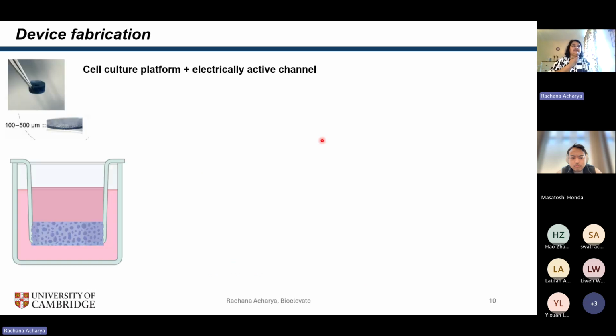So now that we have our scaffold, this is an image of the scaffold when it's out of the freeze dryer. We typically slice this into thicknesses between 100 and 500 micrometers. And what we want to do now is to build an electronic device out of this. Some of you might know that a lot of biology is studied on these transwell inserts. The idea is that you can build your model suspended in your liquid, and then you can test different phenomena happening on the top side and the bottom side separately. So that's what we want to fabricate. Typically these transwell inserts have porous membranes, which are two-dimensional, right? So we want to replace that porous membrane with our scaffold.